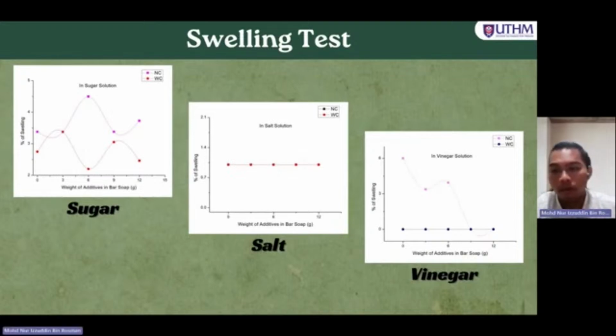But for the vinegar solution, we can see that for new cooking oil, just three samples, which are NC00, NC03, and NC06, have less reaction to the vinegar solution. But for the other samples, the soap completely reacts with the vinegar solution. These formulations are more likely to break down when interacting with the vinegar. Soap containing waste cooking oil is more prone to degrade in an acid environment.